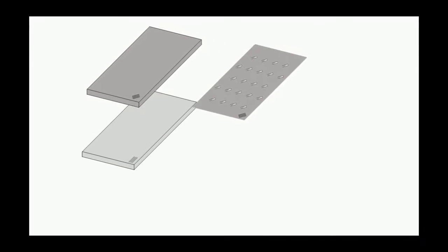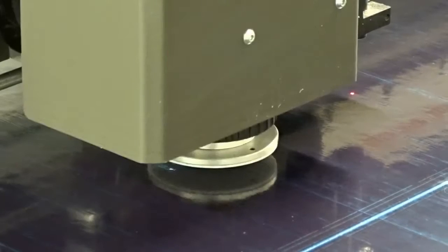The reinforcement units form the core of our concept, so let's look at one in a bit more detail. Each reinforcement unit consists of two thin-ply layers. In the top layer we cut rectangular tabs, and in the bottom layer we cut slits. Note that both the tabs and the slits are aligned with the fiber orientation in their respective layers. These cuts are made using a ply cutter during the regular ply cutting process.